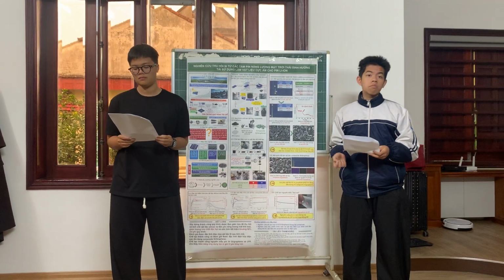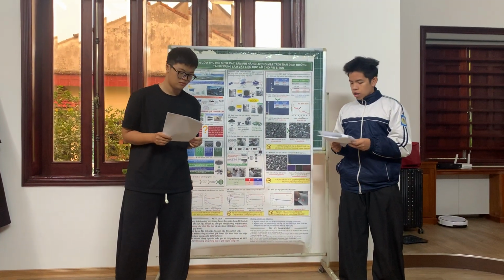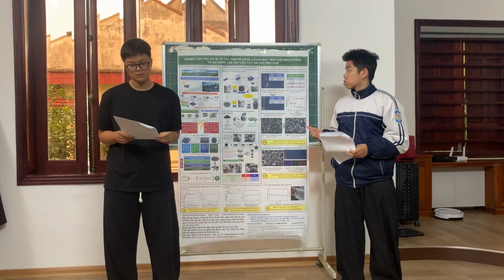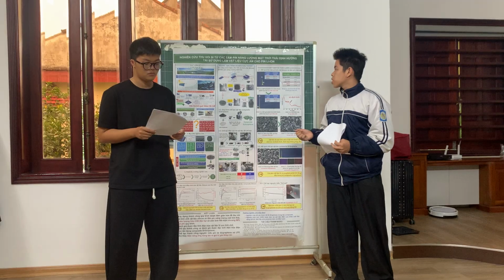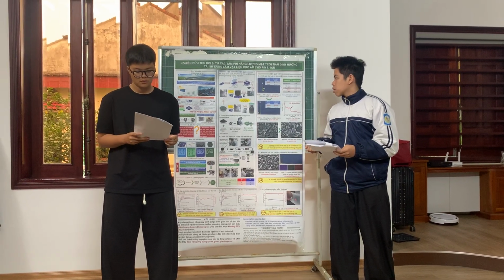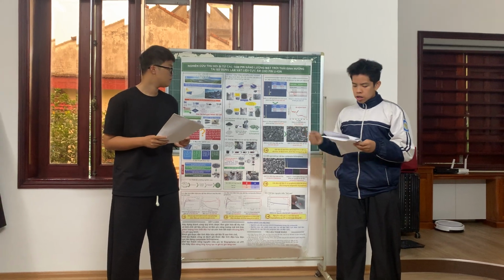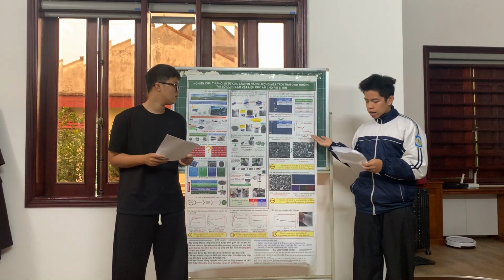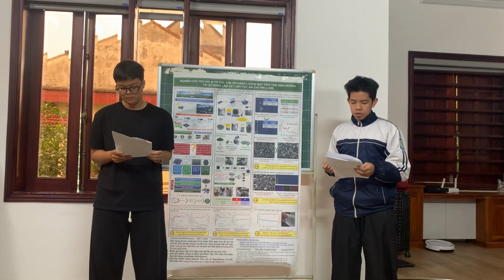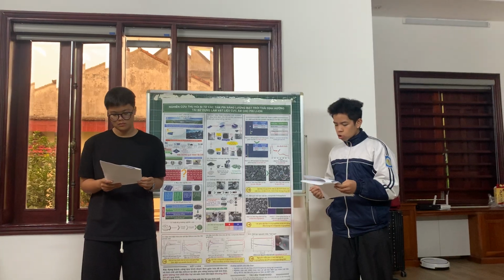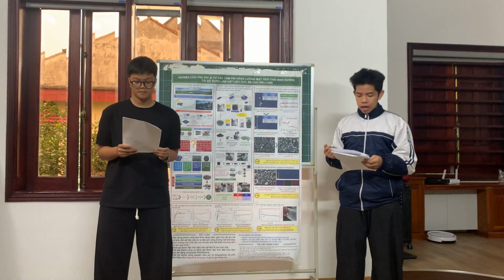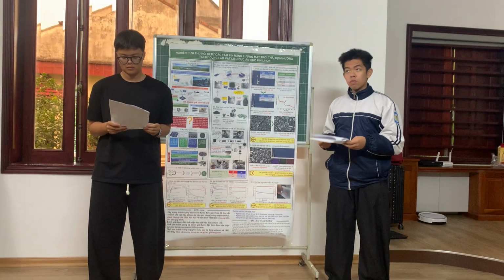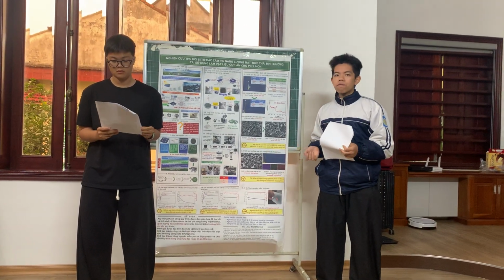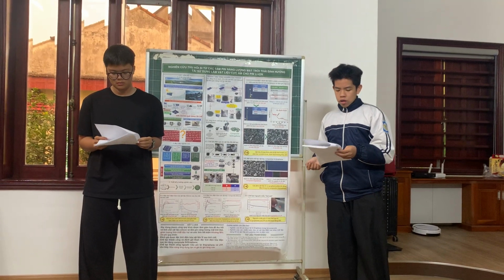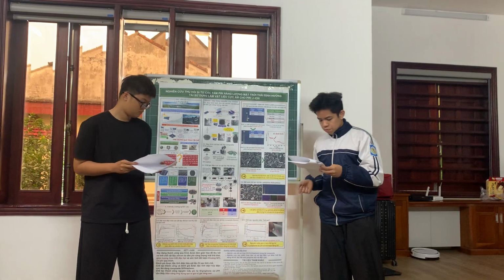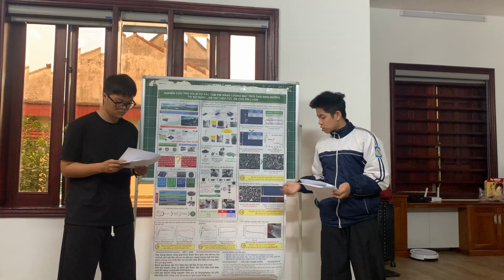The chemical composition of silicon before and after refinement was analyzed by EDX. The results showed that aluminum, which was the main impurity of silicon, was effectively removed, leaving primarily silicon and oxygen. The XRD analysis indicates that the purified silicon exhibits an amorphous structure. SEM images reveal that the particle morphology remains nearly unchanged after refinement, with particle size ranging from approximately 5 to 15 micrometers. The electrochemical performance results represent the core finding of this study.